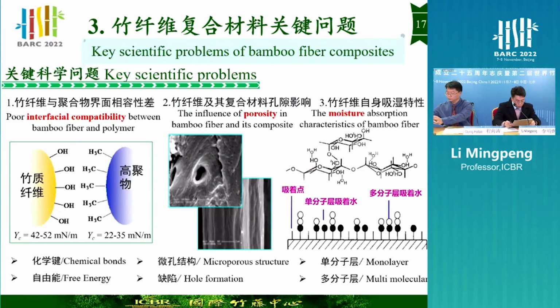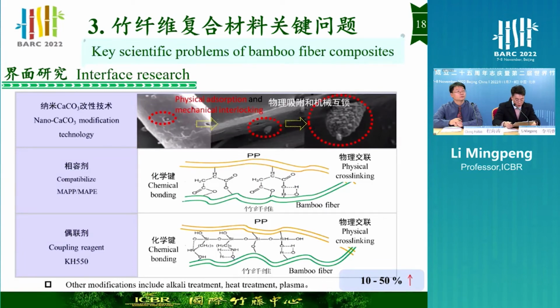So far, there are three key scientific problems in the development of bamboo fiber composites: the poor interface compatibility between bamboo fiber and the polymer, the pores of bamboo fiber composite, and the hygroscopic characteristics of bamboo fiber. About interfacial modification, it mainly consists of nano calcium carbonate modification technology. With the addition of compatibilizer and coupling agent, the properties of bamboo fiber composites can be improved 10 to 50% through interfacial modification.